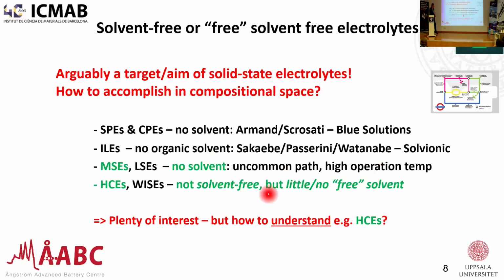I will, however, this one is tricky. I will spend some time with molten salt electrolytes and highly concentrated electrolytes. A concept where you either have no solvent at all, you're making your eutectic mixture, or you have a very limited amount of solvent. So we're trying to get to the solvent-free or free-solvent-free. What does free-solvent-free mean? It means that all the solvent that you have is interacting with an ion, so that it's not really representative of a solvent as a solvent. Solvent in solvent doesn't really exist, so it's solvent interacting with ions.